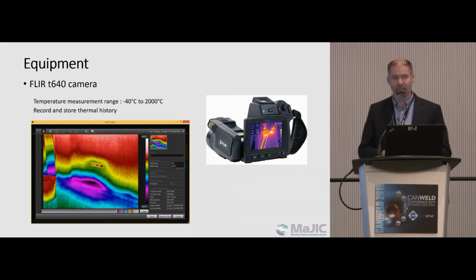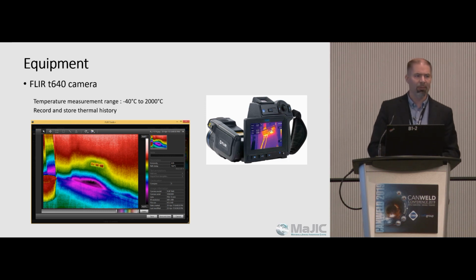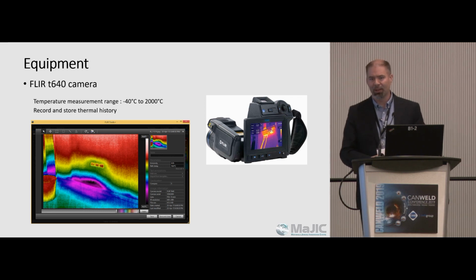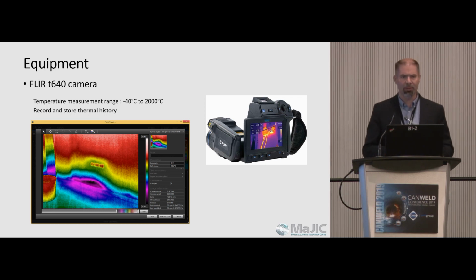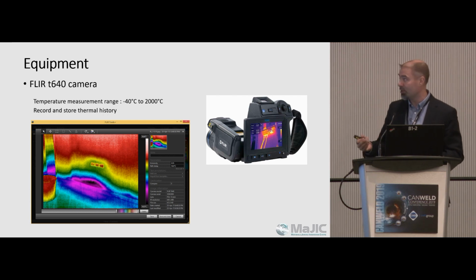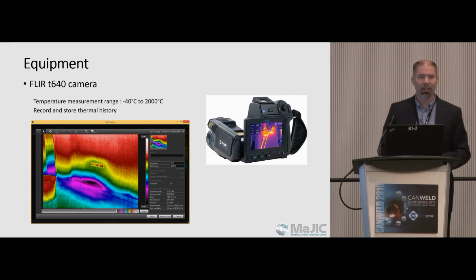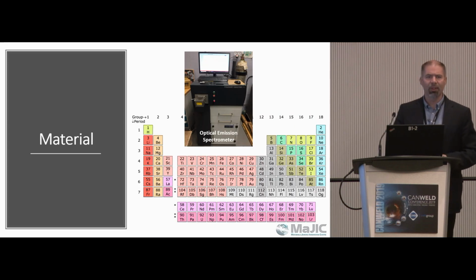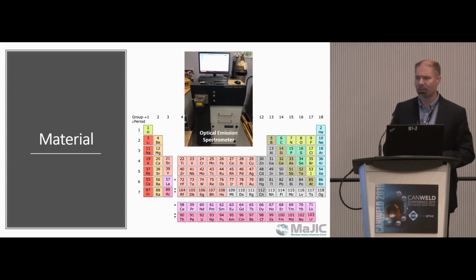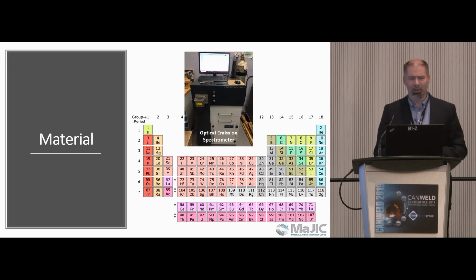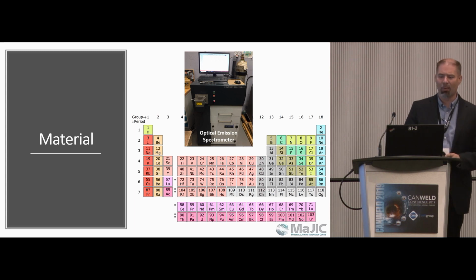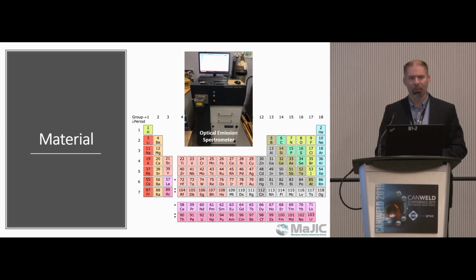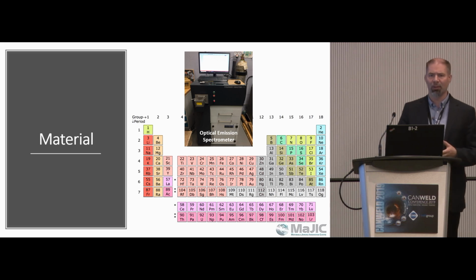So the equipment that we're using, like I said, is off-the-shelf technology. It's not the $350 infrared attachment that you can get for your iPhone, and it's not a $120,000 laboratory camera. This is a standard industrial infrared camera. It's a FLIR T640, and we're using the FLIR software to go along with it. Ranges in this particular camera range from -40 to 2,000 degrees C. The material that we're using, of course, I never believe MTRs wholly, based on batch material sampling. I find never exactly what I want. So using optical emission spectrometer, we verified the actual chemical composition of 3 different alloys that we're looking at.